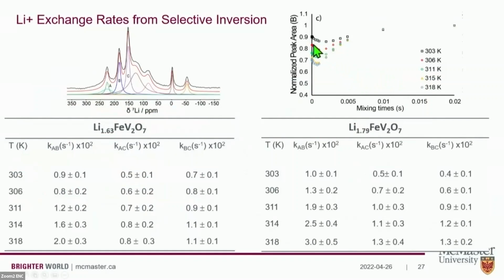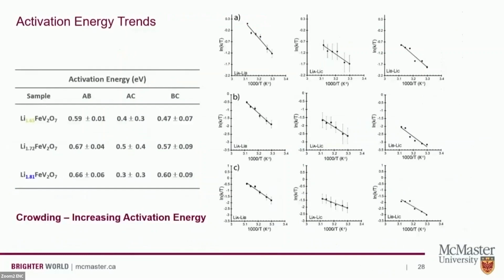This is the experimental data of the transient well evolving as a function of temperature. And we do the deconvolution to extract all of the exchange rates. Exchange rate increases with temperature as it ought to. And so this is self-consistent. And the exchange rate actually is changing as we increase the population of lithium in the structure. So you can think of this as a crowding effect. We go through a phase change, it opens up the lattice a little bit in a way that allows a new dynamic process, but then we're adding more lithium into that structure and populating it in a way that's actually blocking the pathways for lithium conductivity as we continue lithiating the structure. And that shows up for us in a crowding effect, which causes an increase in the activation energy. Tiana has done a mountain of work to deconvolute this.